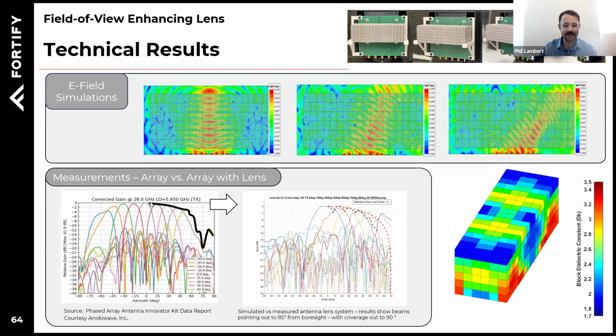On the left, you're looking at this phased array, nominal behavior, which is a phased array from Anokiwave, their development kit, their innovator kit. And you can see this black line is generally where their behavior starts to fall off. So around a gain of around 60, sorry, a beam pointing at about 60 degrees here.